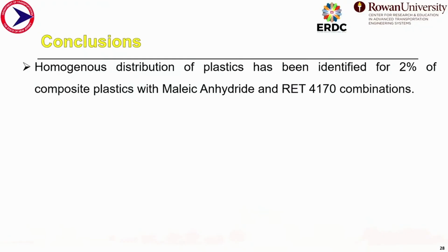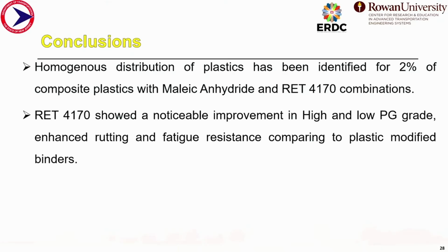First of all, we identified a homogeneous mixture, with no phase separation issue in the wet mixing method with the maleic anhydride and RET 4170 stabilizers with the 2% plastics. Both maleic anhydride and RET 4170 showed noticeable improvement in terms of high and low PG grade, enhanced rutting and fatigue cracking resistance compared to the plastic and maleic anhydride modified binders.